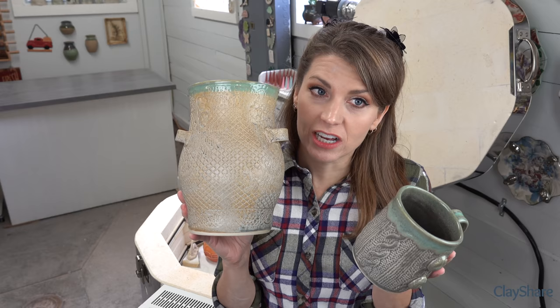This is a Laguna B-Mix pierced bowl where I did some playing with slip trailing - but I went crazy thick with the Chun Blue glaze. This was the last piece I glazed and I realized the Chun was too thick, so it obscures the slip trailing underneath. The color is beautiful but it wasn't so thick that I had crawling or technical issues. I've since thinned the glaze down by adding more water to the bucket.